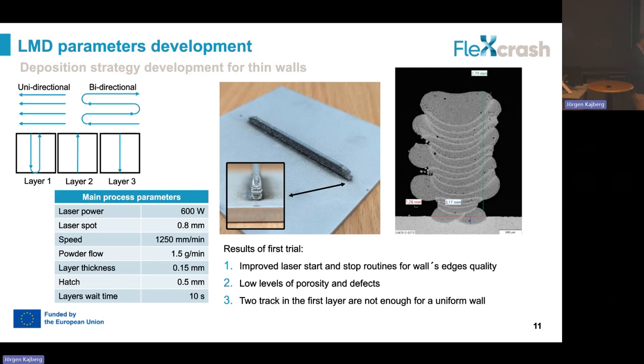Here you can see that two tracks in the first layer are not enough, especially considering what I was saying before about the problem of overheating. You can see here, in the first track that we deposit left and right, the cross-section or the area of the track that we're depositing. In the last layers, due to this overheating effect, the area of the melt pool is almost 5 times bigger than the one in the first layers.